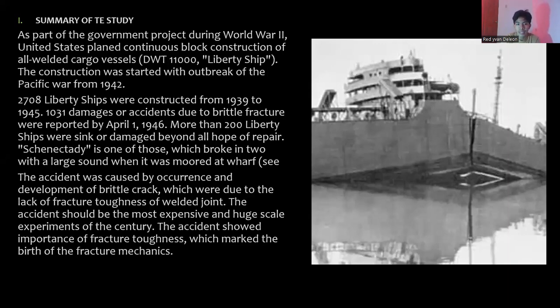1,031 damage or accident cases due to brittle fracture were reported by April 1, 1946. More than 200 Liberty ships were sunk or damaged beyond all hope of repair. The Schenectady is one of those which broke in two with a large sound while it was moored.